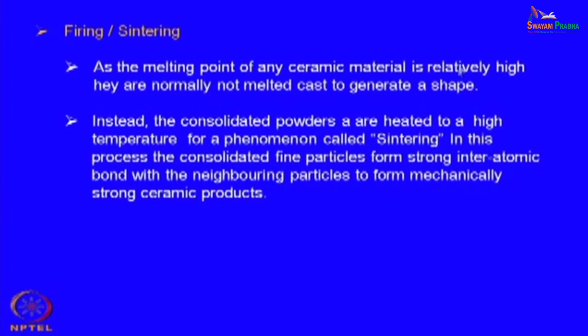Now, instead of melting and casting, the consolidated powders are heated to a high temperature for a phenomenon called sintering. In this process, the consolidated fine particles form strong interatomic bonds with the neighboring particles to form mechanically strong ceramic products. So, this is a common technique, whether you consolidate it by cold isostatic pressing or slip casting or tape casting. Ultimately, all ceramic materials have to be heated to appropriate temperatures, approximately let us say 80% of its melting temperature.